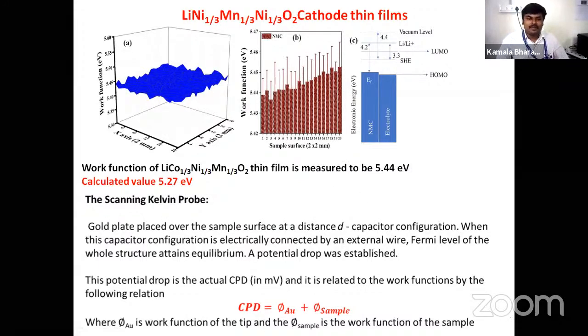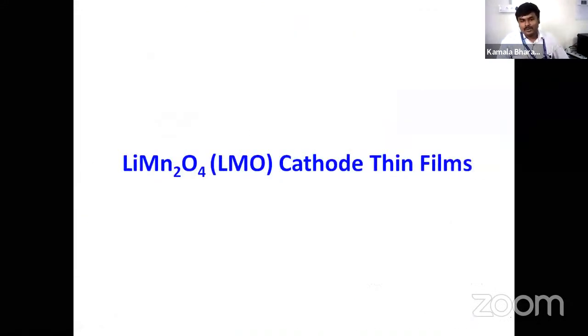So how we measure the work function is we use the parallel plate assembly, where we use a gold plate. So the potential drop across the film and the gold plate is related to the work function using this formula, and we extract the work function of our thin film. Okay, so now I'll move into another material again. It's a cathode material, lithium manganese oxide.